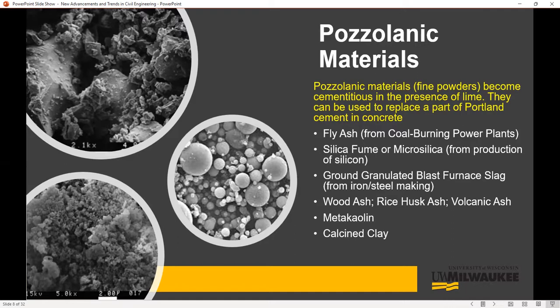So what are some of the major pozzolanic materials? For example, fly ash. In coal burning power plants, in the stacks, they put devices to catch the fly ash from getting out into the atmosphere. In the United States, for example, about 100 million tons of ash gets produced. For many years, they would be landfilled, but then research showed that they could be used in concrete and replace the cement in concrete. This pozzolan, because Portland cement has lime in it, would react with that and act as a cement and reduce the impact of cement, but also improves durability properties of concrete.